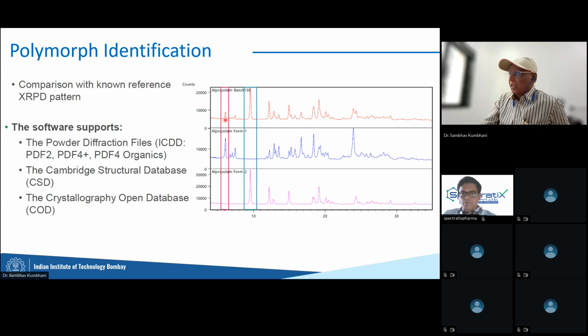If this was completely flat here, and these four peaks were not present, and it was just a plain straight background, then it would have been morph 2 only. But that's not the case. There is some concentration of it available, but it is very obvious that it is not 50-50. Just looking at the spectra, your common sense will tell you this is not a 50-50 combo. This is more like a 70-30 combo, because the intensity is roughly a third of what it should have been if it was a 50-50 combo. I hope this makes sense.